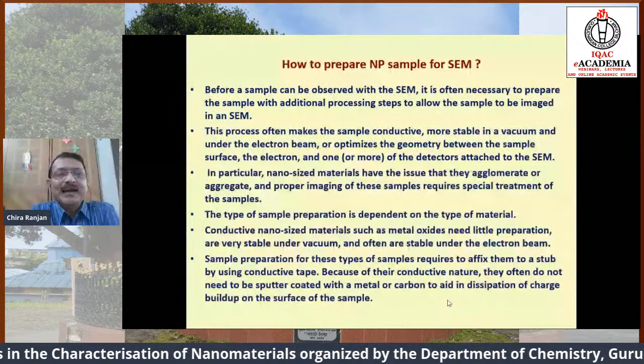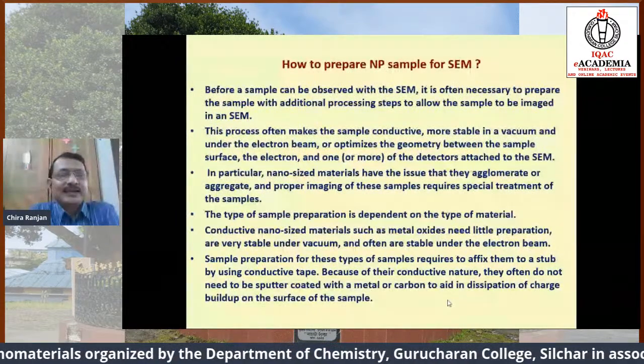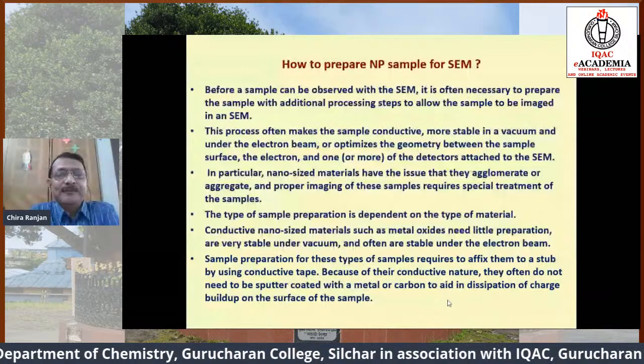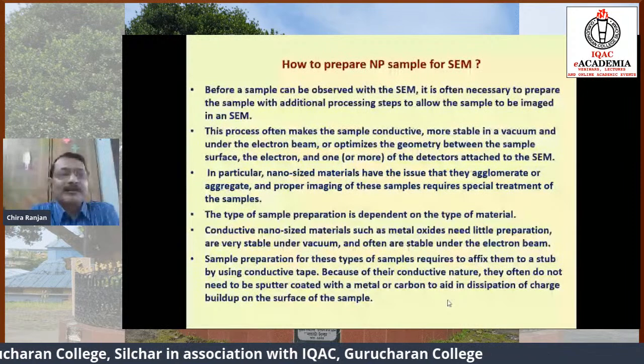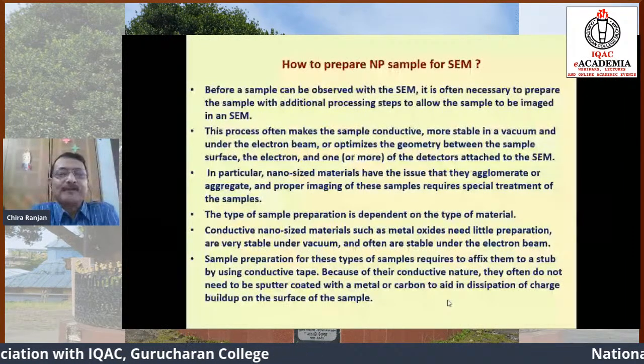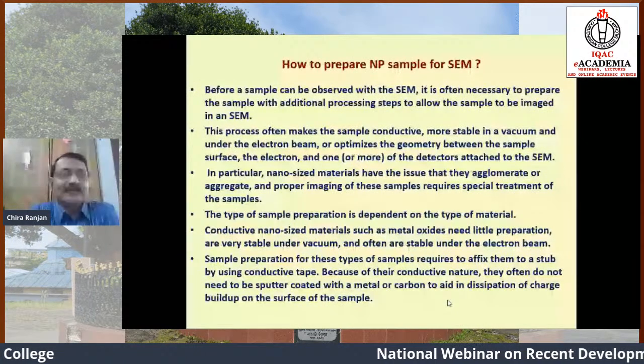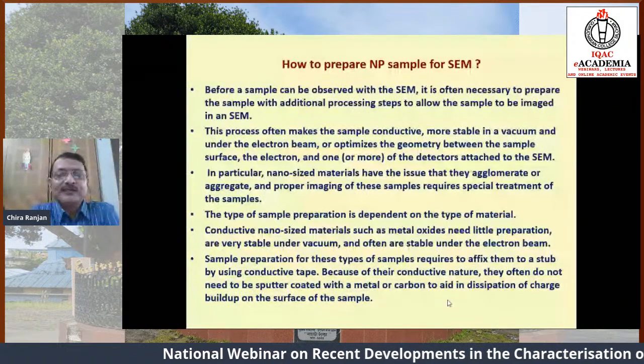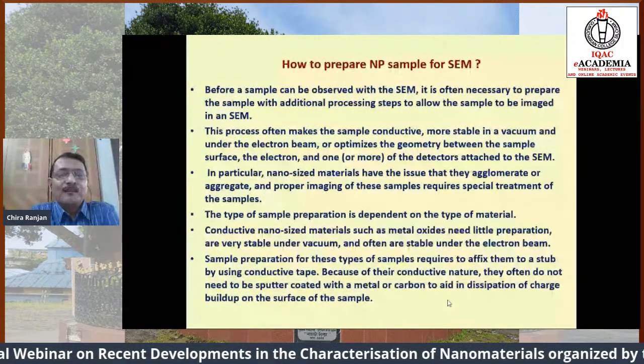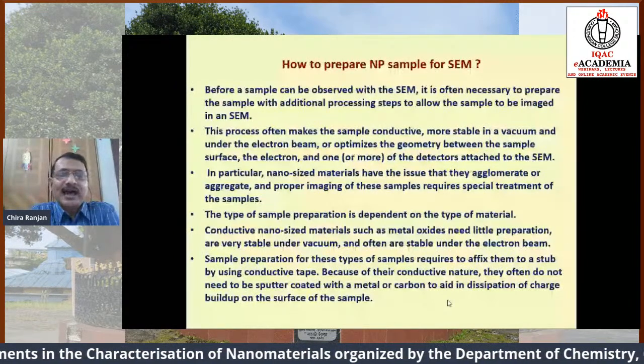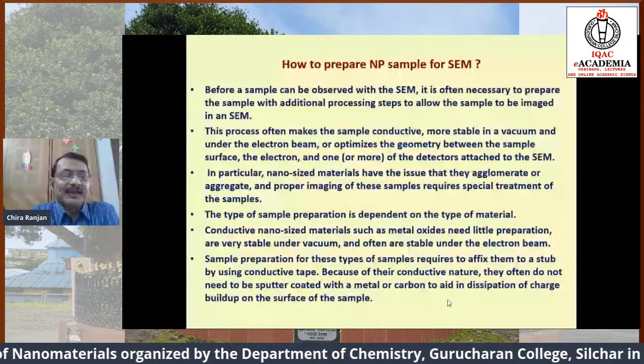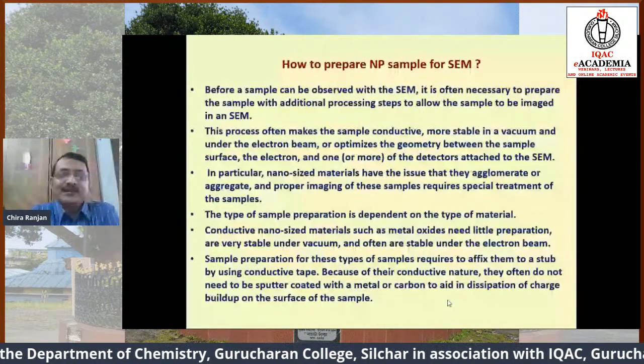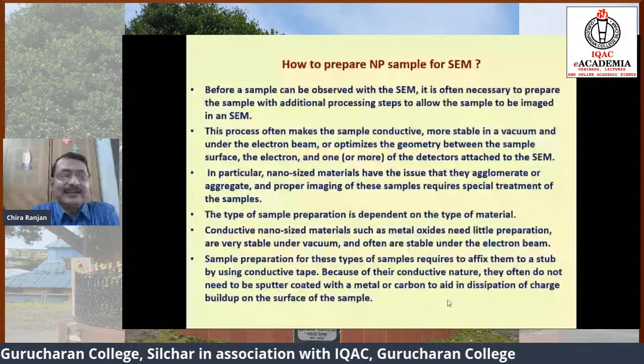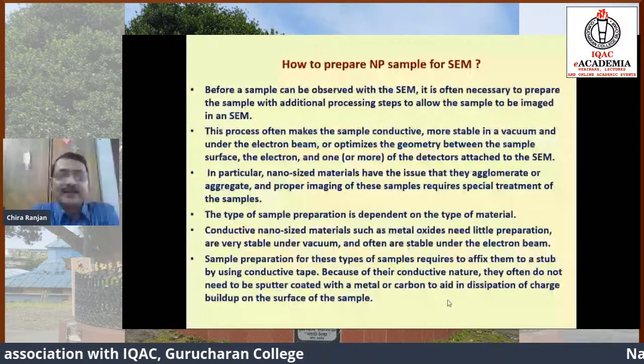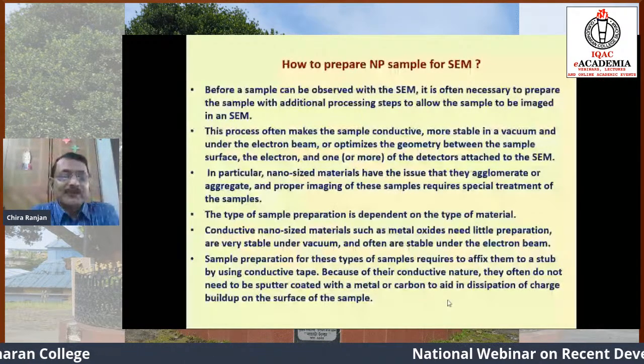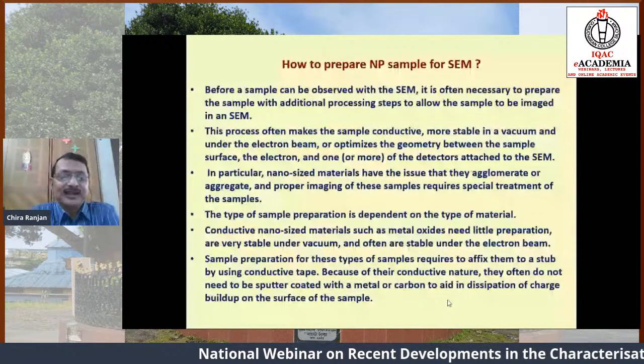So coming to the main aspect of our discussion today, before a sample can be really observed with SEM, it is often necessary to prepare the sample with additional processing steps to allow the sample to be imaged. This process often makes the sample conductive, more stable in vacuum and under the electron beam, or optimizes the geometry between the sample surface, the electron beam, and one of the detectors attached to the SEM. In particular, nano-sized materials have the issue that they agglomerate or aggregate, and proper imaging of these samples requires special treatment of the samples. The type of sample preparation is dependent on the type of material actually.